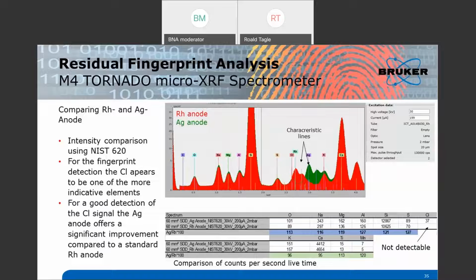So here we see that for most of the elements, the count rates are very similar, and only for sulfur and then chlorine we have really big differences. First the sulfur, because it's slightly differently excited, and for the chlorine we have the problem that with the rhodium tube we don't even see it. It's also not really a certified component of the NIST glass, so there are only traces there.